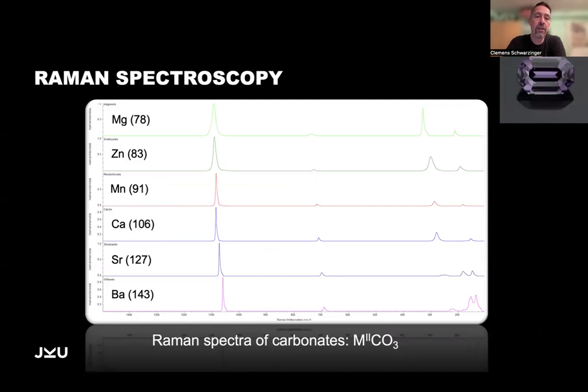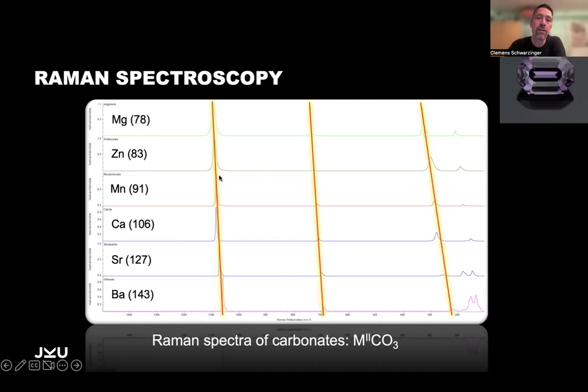And I have a very nice example here on carbonates, and we have here magnesium, zinc, manganese, calcium, strontium, and barium, so different cations for the carbonate. And here the second number is the radius of these ions, from the smallest up to the highest. And these are the spectra. They're all composed of this major peak for carbonate and 2 smaller ones. And if we look here, we can simply place a line that runs through these signals with different quality, I would say. Here we have one peak that's a little bit off, but here the major one.